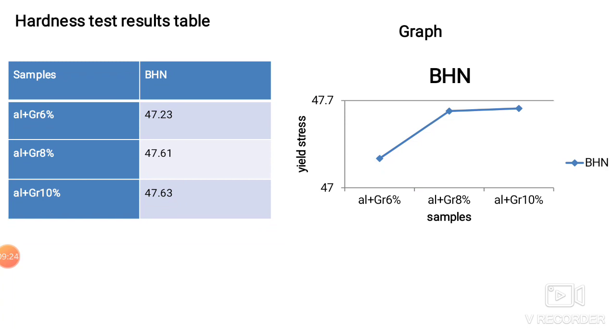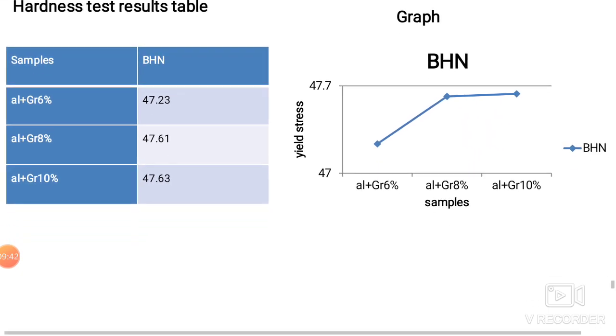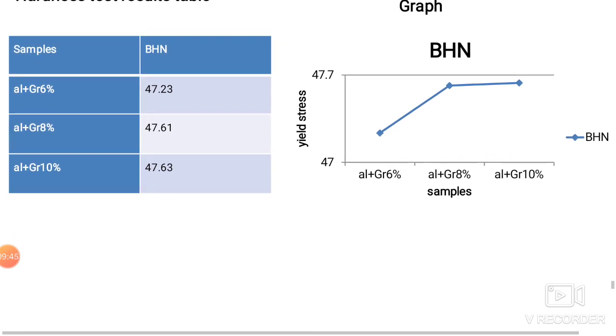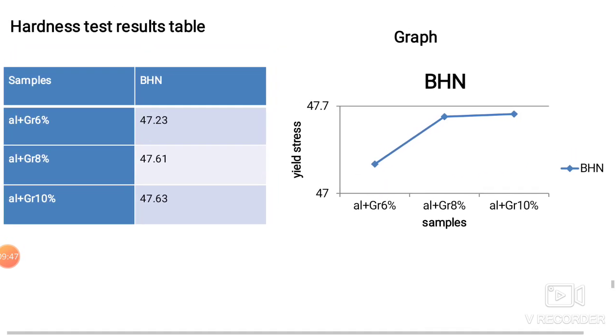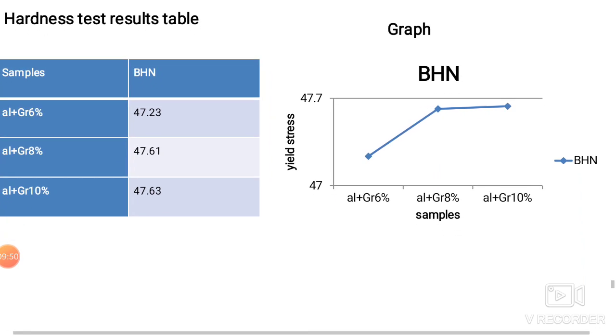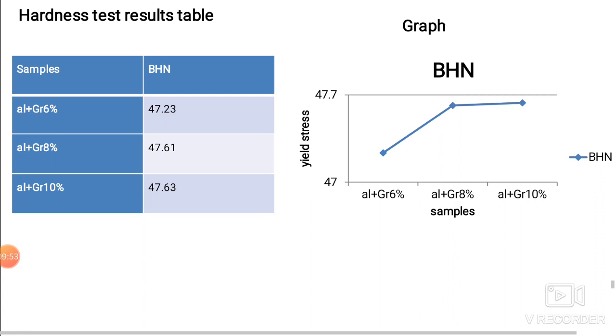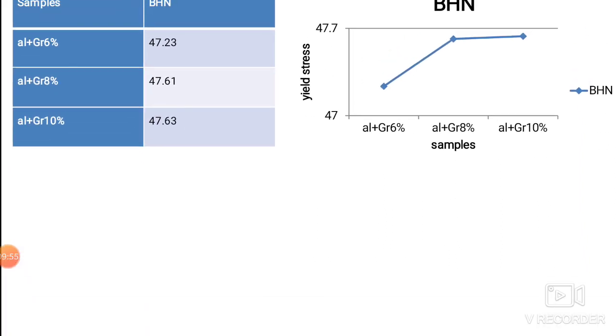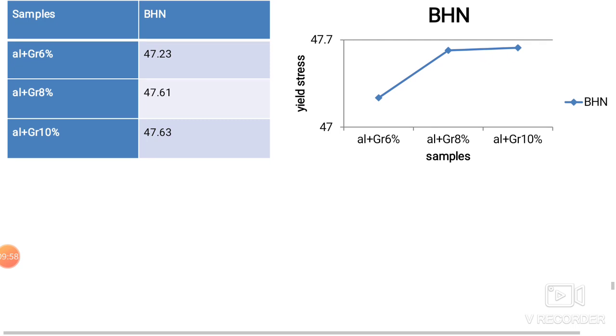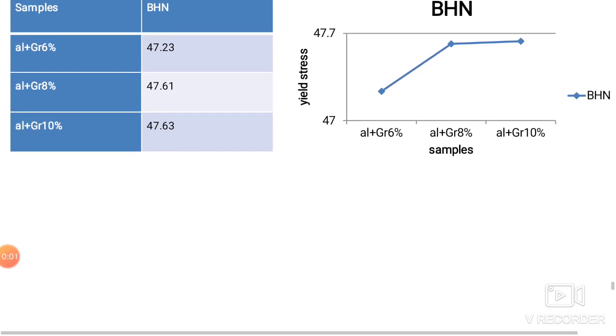The first test sample with 6% graphite and aluminium 7075 showed a Brinell hardness number of 47.23, whereas with the 8% it slightly increased to 47.61. You can see the same with the 10%, where it increased slightly again. On the right side, there is a graph of Brinell hardness number for the different samples. You can see the curve slightly increasing with the increasing percentage of graphite.